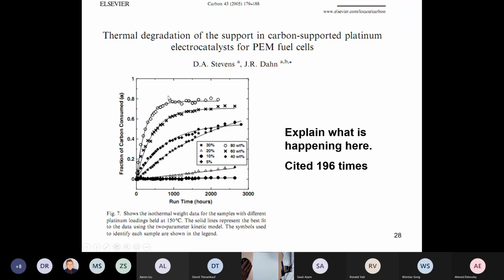So Dave started some experiments, and you've got to appreciate these experiments here. It's incredibly tedious. So he had a whole bunch of carbon-supported platinum catalysts with different amounts of platinum loading, so 10% all the way up to 40% platinum by weight on the catalyst. And he had little containers of these catalysts that sat in an oven at 150 degrees C. And then every few days, he would go off and measure their weight. So at the beginning, he was measuring it daily, more or less. And then later on, you can see, this 2,500 hours is about 3.5 months. And he tracked the weight of these catalysts over time at 150 degrees C.